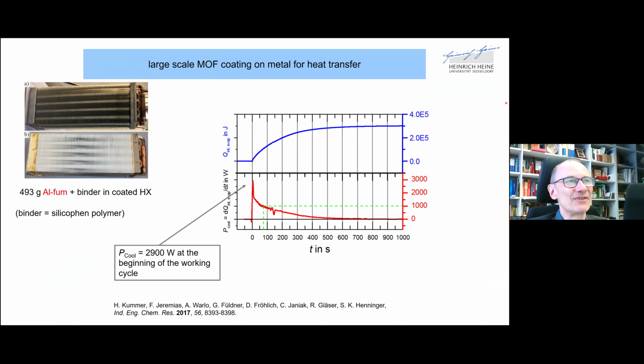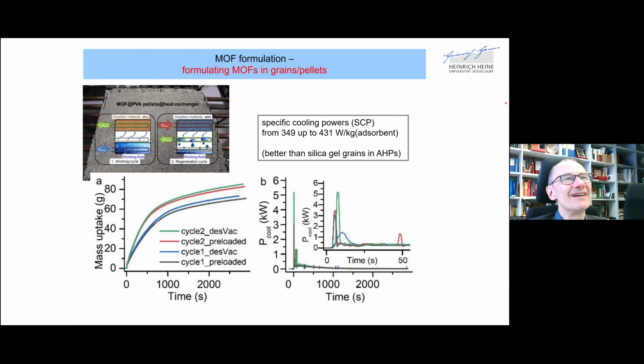I mean, that was only a proof of concept, you could say. You are right that in this process here, we use polyvinyl alcohol. One thing is it's a commodity polymer, very easily available. It has some hydrophilicity, so we could combine it in aqueous dispersion with the MOF crystallites, and that was why we chose this. And it also gave a good composite with the MOF. Because the MOF is to some extent hydrophilic on the outer surface, the PVA could stick to it, and we could form these spheres which you see here on the picture with the PVA.